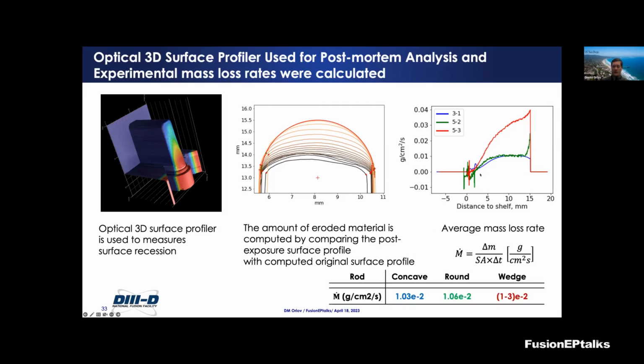The concave rod is given here in blue, the round rod in green, and the wedged rod is the red curve. That's the highest ablating case, and we could calculate that to be about 1×10⁻² grams per centimeter squared per second. So these were our experimentally measured ablation rates in this case.